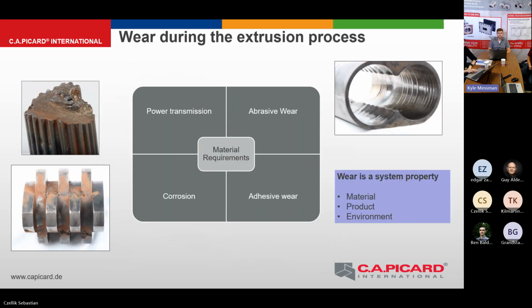Here is a summary of what we can see in an extruder for wear mechanisms, starting with the power transmission. A shaft that got too much torque looks like this: it breaks. We don't see that very often, but it happens from time to time. Then I really like this kneading block because you can see such heavy corrosion on it. It's an issue in many processes, and we are seeing corrosion more and more.